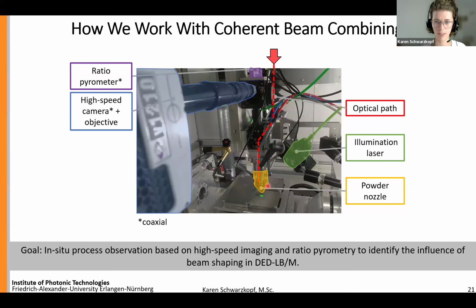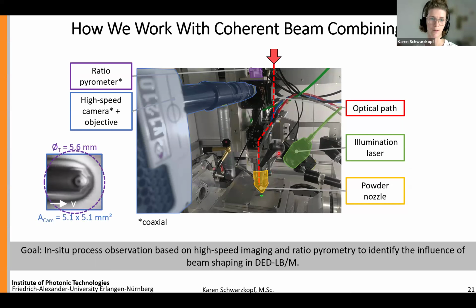Important to mention is again the powder nozzle, which is highlighted here in yellow, where 3 different channels from the powder supplier are merging together, feeding powder into the melt. On the left side, you can see the dimensions of the field of view from the camera coaxially, and also the ratio pyrometer up here. Maybe one short announcement for the ratio pyrometer. It's basically an approach that allows to derive temperature information only based on a ratio between 2 frequency spectra. So we do not need emissivity values in order to get thermal information.